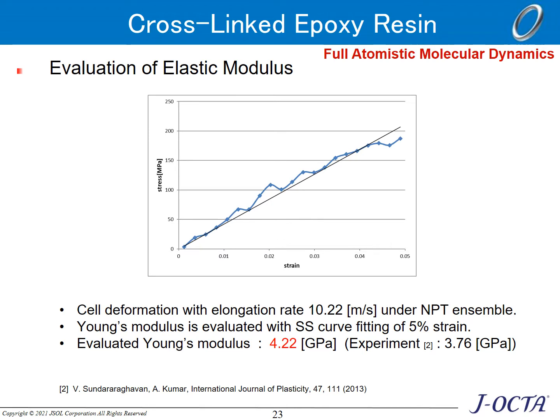By applying uniaxial elongation to the structure obtained by reaction calculations, the stress-strain characteristics can be obtained. Again, it should be noted that a higher speed deformation was applied here than in the experiment. But the obtained Young's modulus is comparable to that of the experiment, because the epoxy resin is in a glassy state at room temperature. It is possible to confirm by molecular simulation how these mechanical properties are affected when the molecular structure of the epoxy resin's main agent and curing agent are changed.